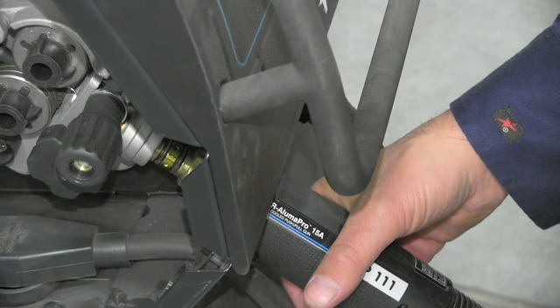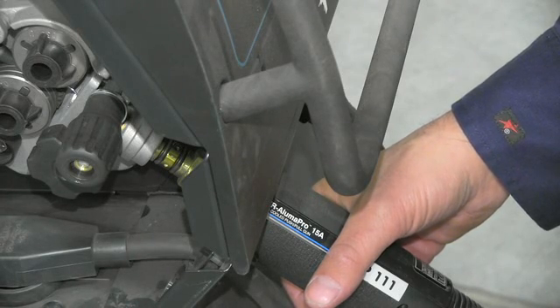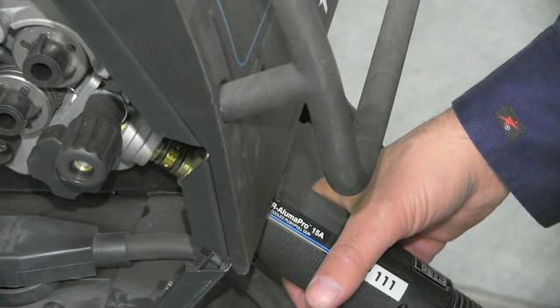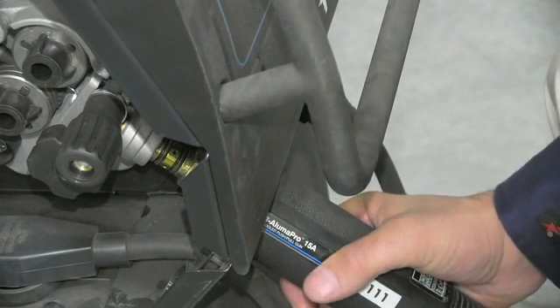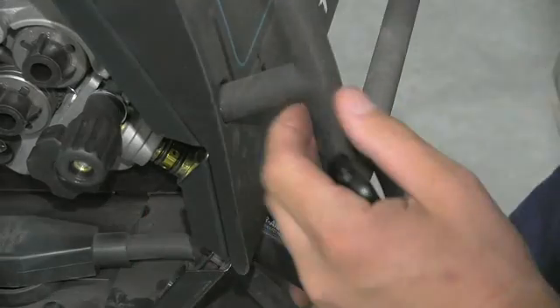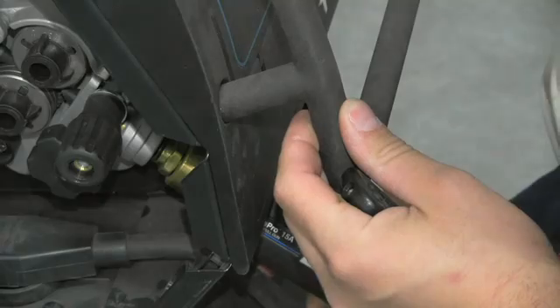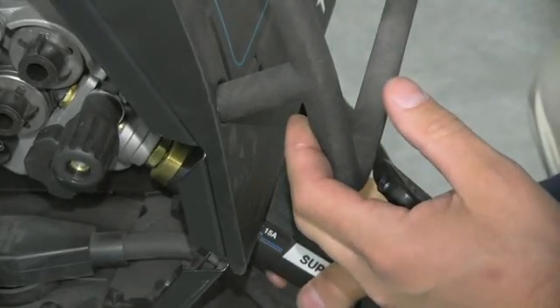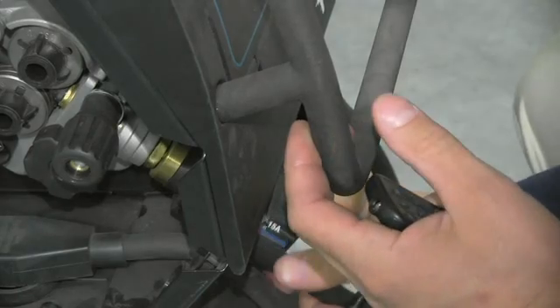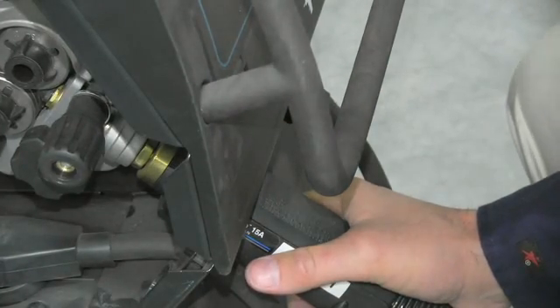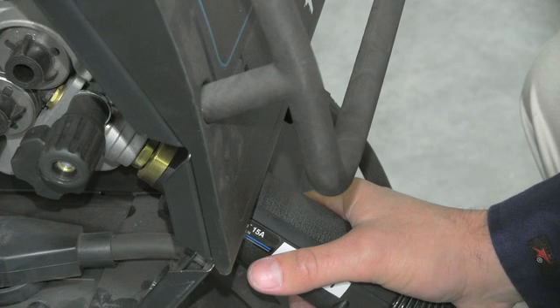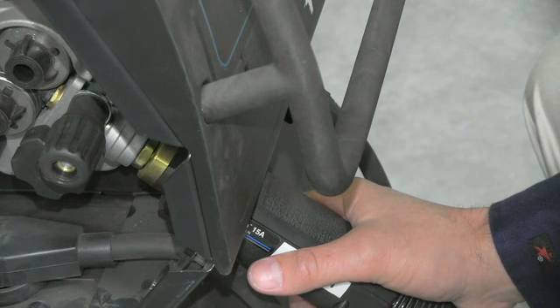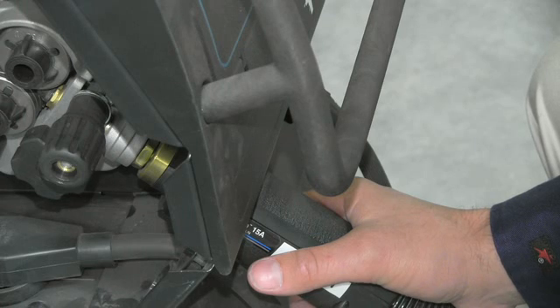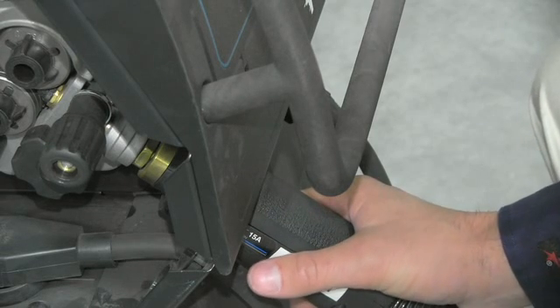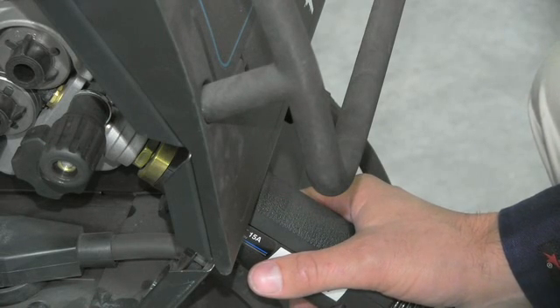Another system that is common for having the O-rings not get completely seated when installing the gun is a push-pull system, similar to a Miller-Matic 350P. So here is the push-pull power pin, and you can see the O-rings down here. A lot of times this gun is very tricky to install because it's really tough to push all the way in. I've had cases where a customer will buy a brand new machine and call back and say, hey, it's welding real poorly. You won't necessarily see porosity with aluminum when this happens. You just won't be able to weld. The weld will dig right through the aluminum. It'll burn right through it, and it's kind of awkward looking, but it's not necessarily porosity like you'll see with MIG welding on steel. So when they call, they may not say it's porosity, just that it won't weld.